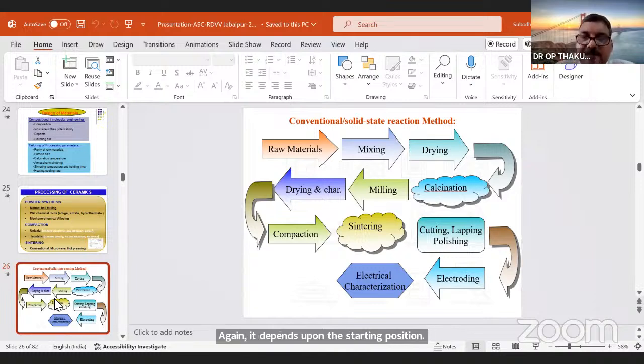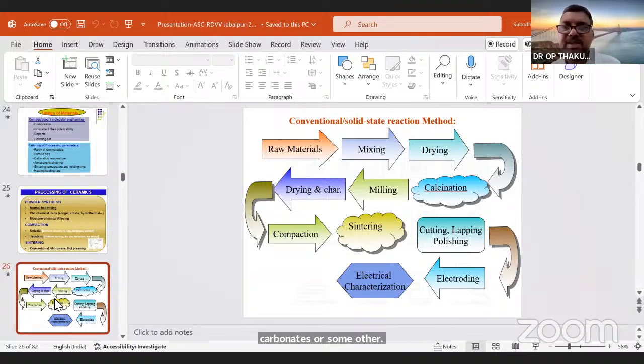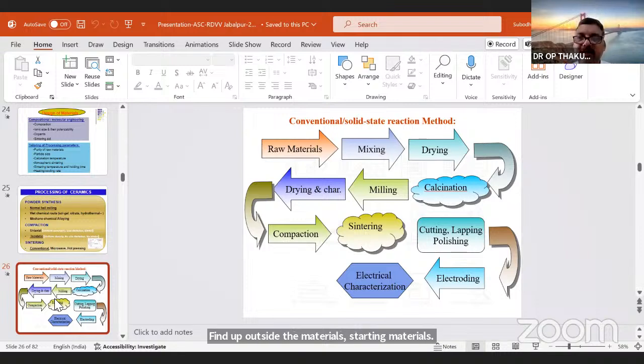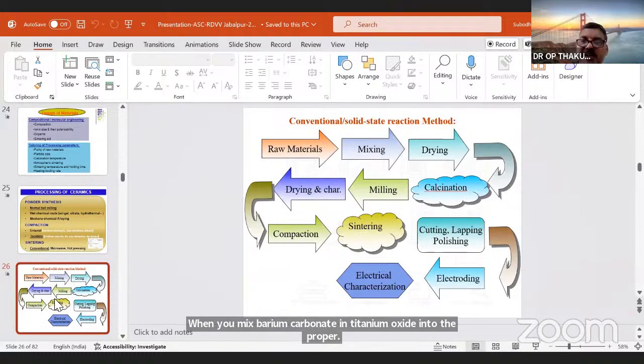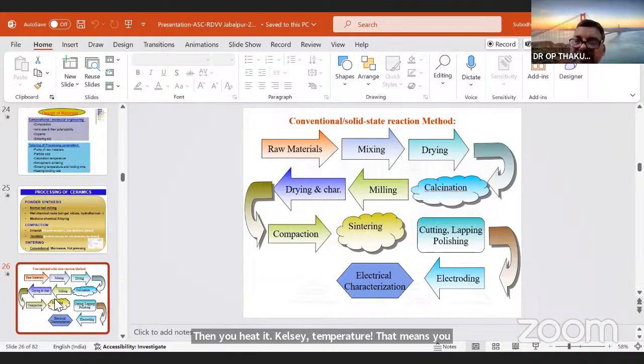And the purpose of calcination is, sometimes for oxide ceramics you are not taking oxide as a starting material. Sometimes you take carbonates or some other form of starting materials. So just to evaporate carbon dioxide from the carbonate starting materials and convert into oxides, you have to do the calcination. Suppose for making barium titanate ceramic, generally you start with barium carbonate and titanium oxide. When you mix barium carbonate and titanium oxide in the proper ratio, you heat it to the calcination temperature. That means you are decomposing barium carbonate into barium oxide, BaO plus CO2. That means you are eliminating CO2 from your starting chemicals.